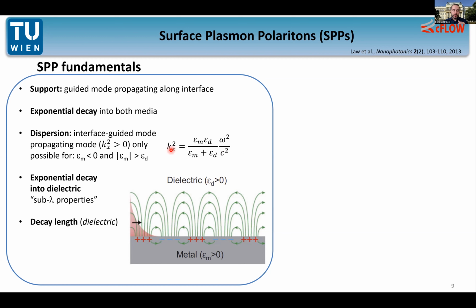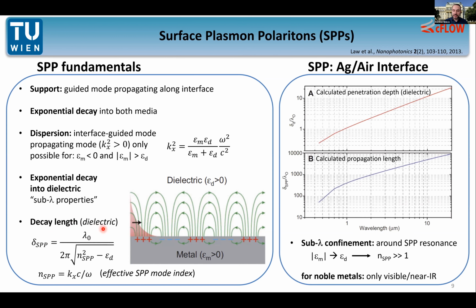If you look at the dispersion, which is basically how different wavelengths can propagate along the surface, then we see that we have a strong dependence basically on two parameters. One parameter is the permittivity of the metal, and the other one is the permittivity of the dielectric. Their ratio defines how the mode is propagating along the surface. So we can define a certain condition for mode propagation, which tells us which combinations of materials can be used together. And we can then, for example, calculate the so-called decay length. I spare you details on the formula. Just important that you know that it's wavelength dependent in this case.